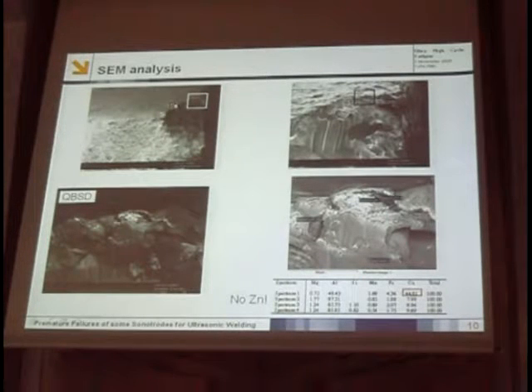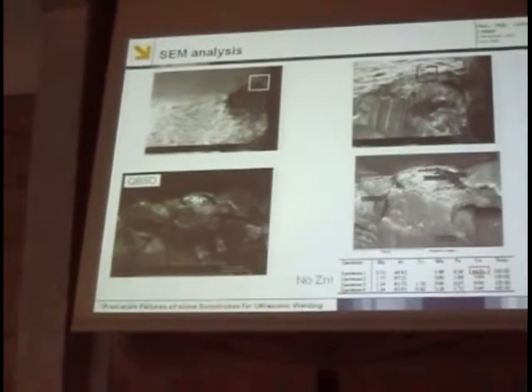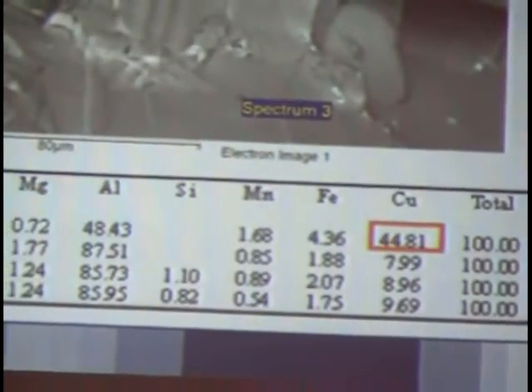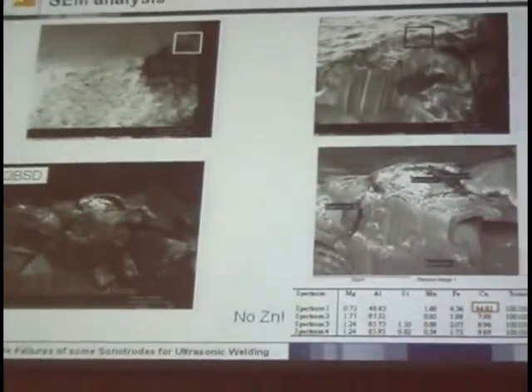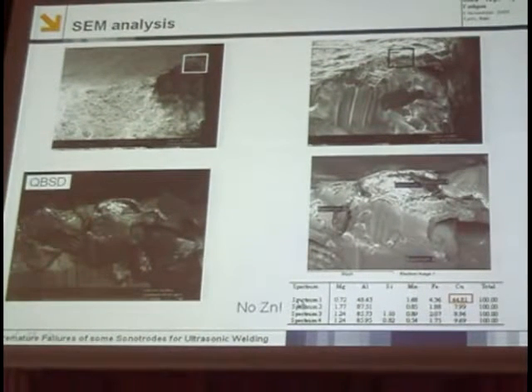I saw different defects of this kind in the fracture surfaces that I analyzed, but I also saw a different case, and this is the second type of defect I saw on the fracture surfaces, and this is a subsurface defect. You can see here, again with the QBSD diffusion method, there is some particular concentration of copper just below the surface, not in the interior this time, but just below the surface. This is really peculiar again, because this huge amount of copper should not be present here. And also in this case, no zinc was observed in the alloy.